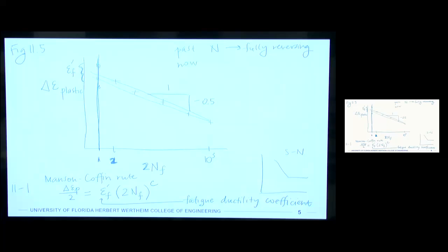So now for low cycle fatigue, we have Nf, right, which is a half of a strain cycle. So that's why we always work with 2Nf, right? So it's just a slightly different definition. Okay. And then c, the exponent there, is a fatigue ductility exponent. And it's the slope of that line on that plot. So this is the relationship that we have for plastic strain.